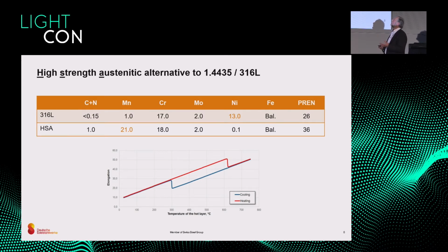How to avoid nickel in this case? We move from nickel to manganese. It's also an austenite stabilizer. And we want to increase the strength, and therefore we increased the amount of carbon and nitrogen. Actually, the 316L has a low carbon and nitrogen content. And this causes, due to the structure of austenite, it is very soft. We call the 316L a steel without properties. It's even not corroding.